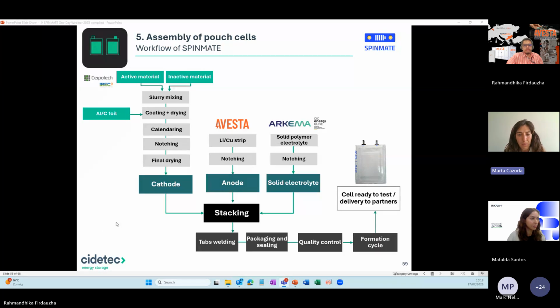And once we have all the components of our cells, we do the cell stacking and tabs welding, packaging and sealing, again some quality control that we will see in a minute. And we do a formation cycle. A formation cycle is like a preliminary electrochemical formation that allows us to have a controlled formation and first discharge of these cells before having the following electrochemical testing and delivery to the rest of the partners of SPINMATE to do their characterizations.